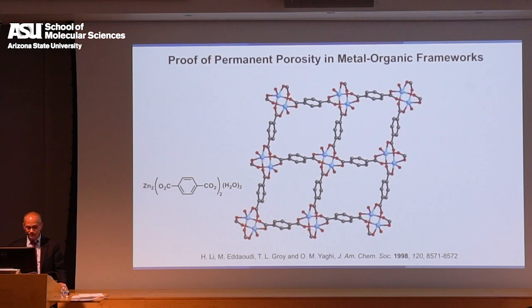So those coordination polymers containing neutral linkers are not viable for the things that I'm going to talk to you about. So immediately then, in 98, we had to show that, in fact, you can make a MOF, not just crystalline, but that the pores can remain open in the absence of guests. And we use the strategy of carboxylates with metals to make these aggregates and link them up into extended structures such as what you see here.